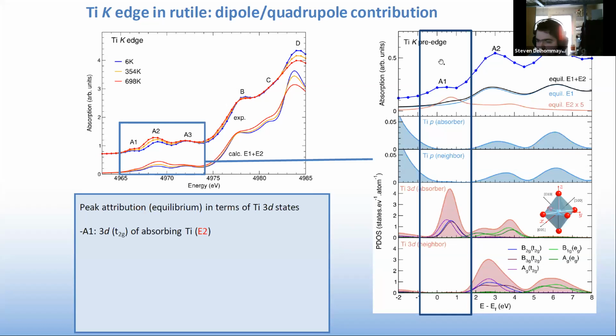so E2 contribution. And indeed, when we look at the density of states, we only see the 3D T2G state, and so we know that the A1 peak, at least at equilibrium, is a signature of a direct transition from 1s to the 3D T2G of the absorbing titanium.